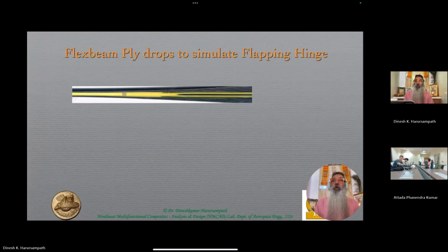Thanks so much. So if you see, to move from a very large number of what we call plies or laminae, we want to get to a smaller number at the left end in order to simulate the flapping hinge, to some extent the bearing as well. When you want to do that, you do not want to suddenly drop a large number of plies, because that creates a discontinuity and therefore stress concentrations, which will become a source of delaminations, which means two plies or two layers of lamina, which get separated from each other.